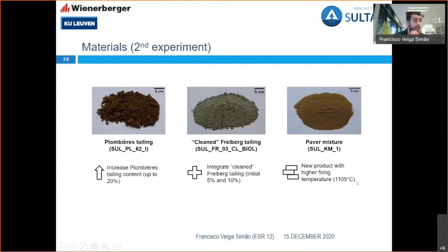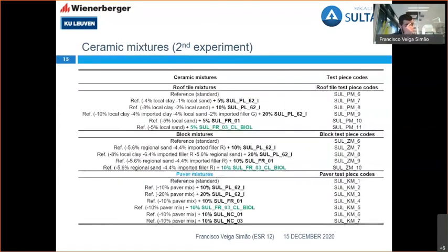And I integrated a new ceramic product. I integrated the mining waste into a new ceramic product, with higher firing temperatures. And in this case, I also integrated all the unclean mining waste, because if it fires higher, it means more volatilization, so perhaps less sulfate content at the end. On this second experiment, I produced several ceramic mixtures, increasing the Plombières and also comparing the non-clean and the clean Freiberg tailing.